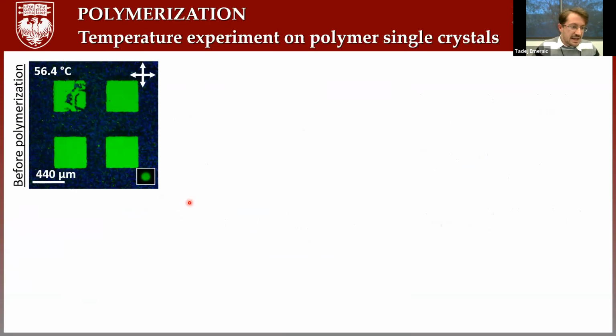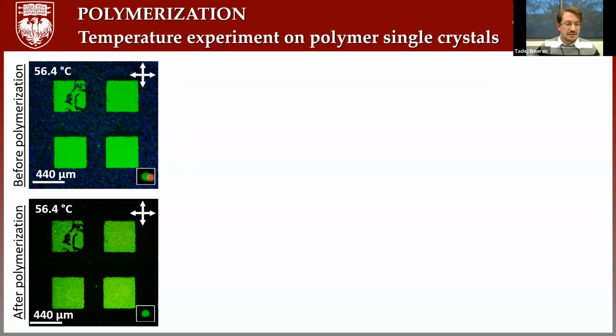So to do this, we did it in this way: first, as you can see here, we can see four sets of lines, right? For the formation of single crystal in blue phase that reflects the green light. This is before polymerization. So once we reach this state, then we shine with light, the system freezes. Based on the diffraction patterns here, we can see that the blue phase with this lattice orientation remains the same.